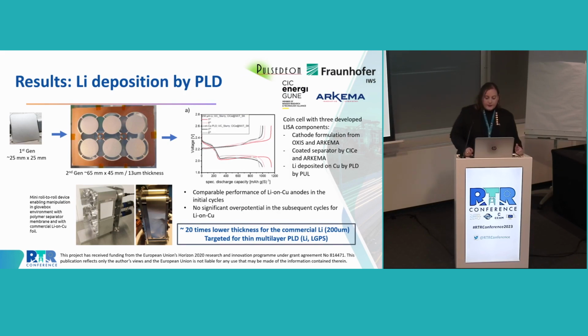Regarding the lithium anode developed by pulsed laser deposition, we were able to reduce the thickness of lithium to 13 microns of lithium deposited on copper. This is a reduction of more than 20 times compared to the commercial lithium that you can find. Here I am showing you a coin cell test level, comparing the reference materials versus the 3 components developed in the LISA project. One is the cathode formulation developed between Oxis and Arkema, the coated separator with this hybrid solid electrolyte, and the lithium deposited on top of copper. What you can see here is that the behavior of both cells is mostly the same with the reduction of lithium thickness. This means reduction of weight and also volume.